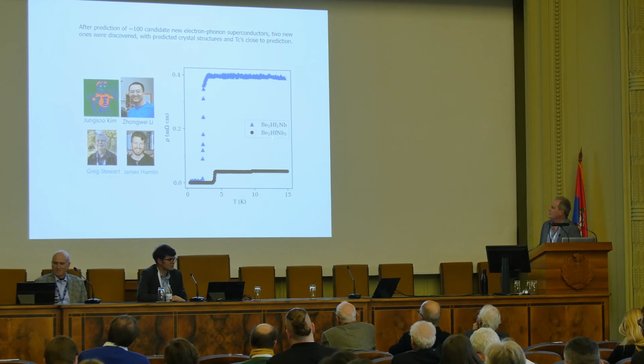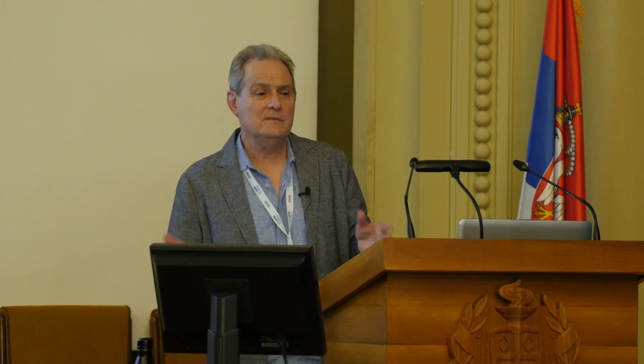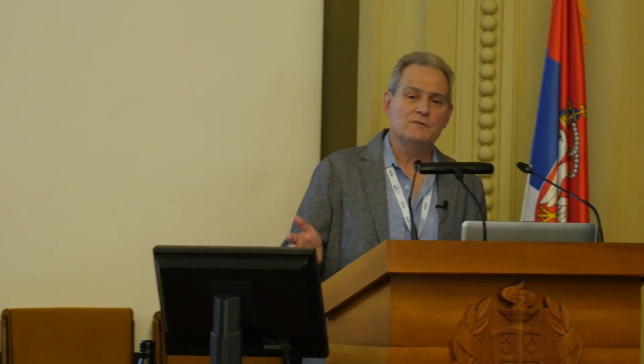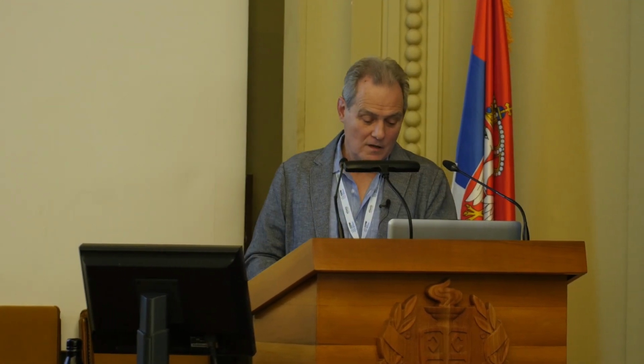These are beryllium compounds, and they're not high temperature superconductors. But the goal of the project really is not to discover a high temperature electron-phonon superconductor at ambient pressure, but rather to find a new superconductor which might be 30 Kelvin or 35 Kelvin, because that would immediately have, provided it's 3-dimensional, enormous technological implications for magnet technology and things like that. So that's pretty much it.